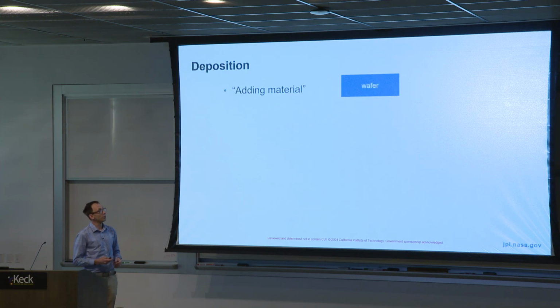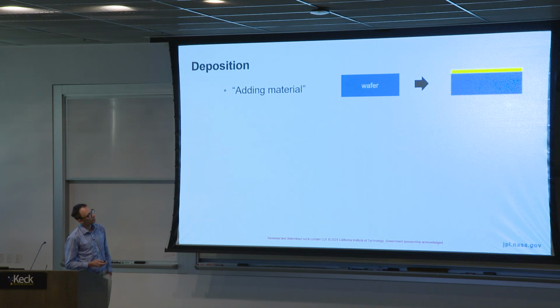Deposition, so adding material onto your wafer, might be as simple as this. You have your wafer, you add, that looks like gold, so you add it just on the top of your wafer, you deposited it somehow. And it's an important thing that took me quite a while to get used to. Normally when you think of a material, let's say silicon dioxide, you think of it as a well-defined material that always has the same material parameters. That's not really the case. Depending on what methods you're using to deposit it, you typically get slightly different refractive index or density. You always end up with some amount of impurities in there, and they translate into the material properties that you end up with. So that's one aspect to consider when you're choosing your method of deposition.